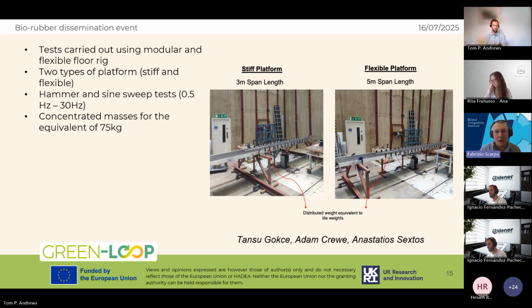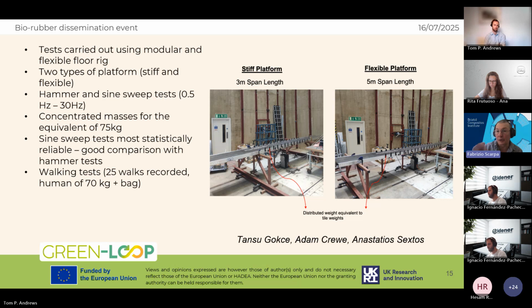To assess the performance of these types of panels, we have designed in Bristol a flexible, reconfigurable platform to host the panels at different heights, and also to perform different types of ISO standard tests using impact, sine wave electrodynamic shaker, but also walking tests. And in terms of tests with hammer and sine sweep, we look at the frequency range between 0.5 and 30 Hz, which is typical of floor vibration in most of the available buildings. We have also considered the presence of concentrated masses equivalent to 75 kilograms to consider the static presence of persons already sitting on those panels. But we also performed a walking test.